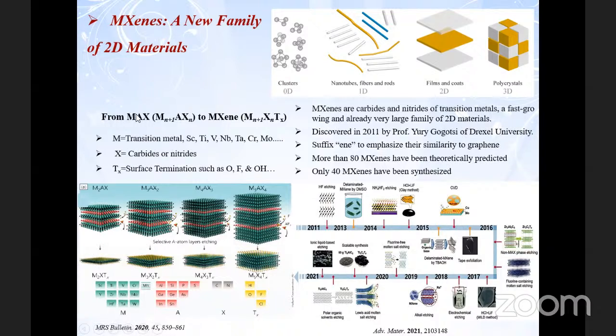We use mostly the MAX phase, where M is the transition metal like scandium, titanium, A is the aluminum, and X is the carbide and nitride. So if you look at the history from 2011 to 2021, mostly in the synthesis or development of this material, you will see mostly hydrogen fluoride, a very highly toxic and dangerous material, being used to remove the aluminum, the A material.